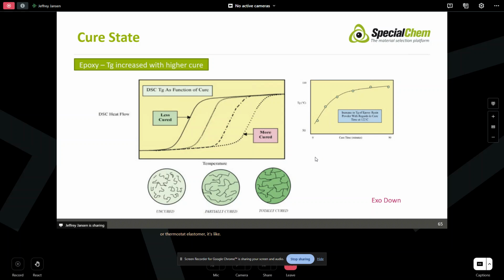Okay, the more cured the material is, for thermoset plastics, the higher that glass transition temperature is going to be. And typically, we're trying to maximize that reaction. So again, much like we did with some other test techniques we talked about earlier, we can assess the material and understand how cross-linked the material is by where that glass transition is. Again, it does require establishing some level of what I'll call calibration curves. But at a minimum, if you just run your undercured material and your fully cured material, you can understand where that glass transition is.